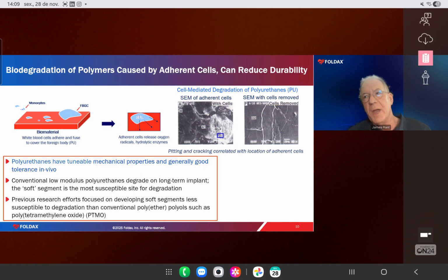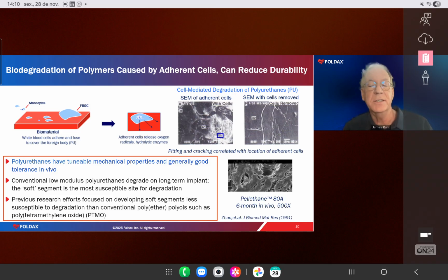So going back, certainly 20 years ago, people were searching for ways to use different kinds of soft segments that are less susceptible to damage, oxidation, and hydrolysis. A lot of these soft segments at the time were based on polyether chemistry. In other words, it has a couple of carbons and an oxygen, and people tried to, and very successfully in some sense, to increase the hydrocarbon concentration in the soft segments and create more stability. And that works up to a certain point, but not completely. And this is out of sequence, but you can see the damage that's actually done with a soft polyurethane at a somewhat higher magnification.